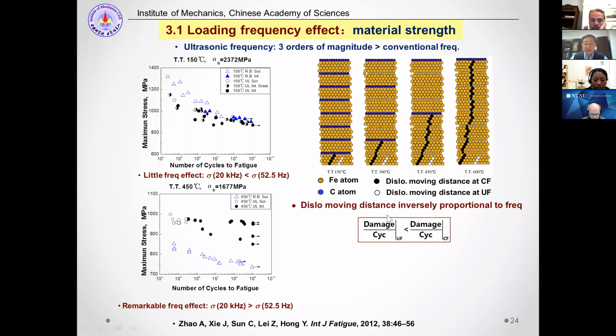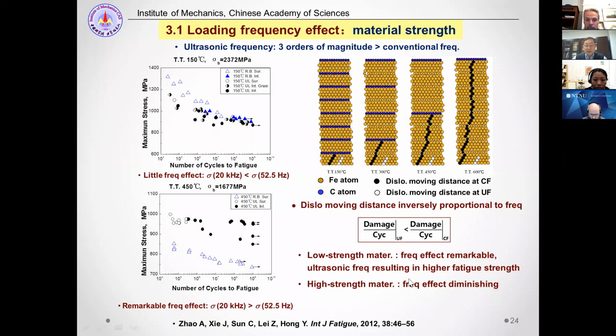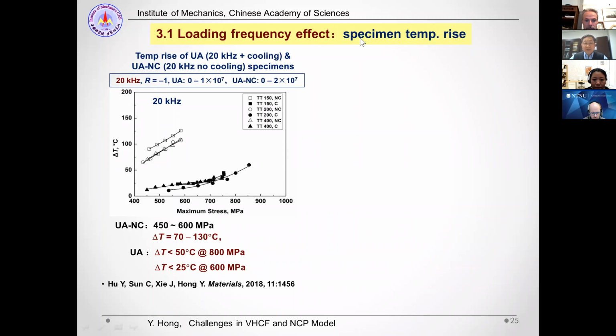So the dislocation moving distance will be inversely proportional to the loading frequency. So for this case of low strength state material, the damage per cycle will be larger than the damage per cycle of the ultrasonic loading process. So we say that for low strength material, the frequency effect is remarkable, but for high strength material the frequency effect will be diminishing. And I also would like to mention the temperature rise under different loading frequencies. That's a loading frequency effect.